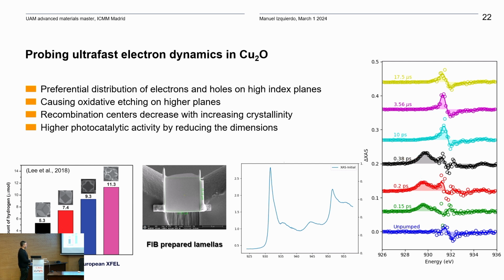And then you see here that there are changes in the L3 line, and because we have the megahertz repetition rate, you can follow how this excitation of the system evolves. In this particular case, we went up to 17.5 microseconds. If we had more pulses, you could go up to 250 microseconds. And you see that some of the excited states are long-lived in the compound.